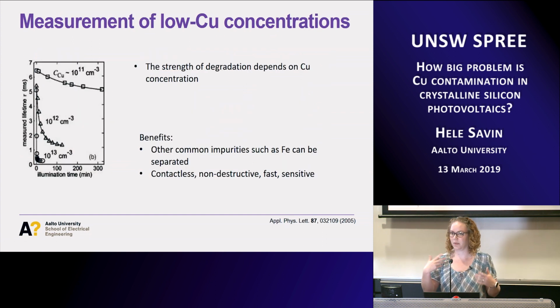And to make this method quantitative is also relatively simple, because we have shown that the copper LID will depend greatly on how much copper you have. If you have really a lot of copper, you have this huge degradation here. If you have a little bit less, then it saturates to a higher value, and if you have even less, then it saturates even further.